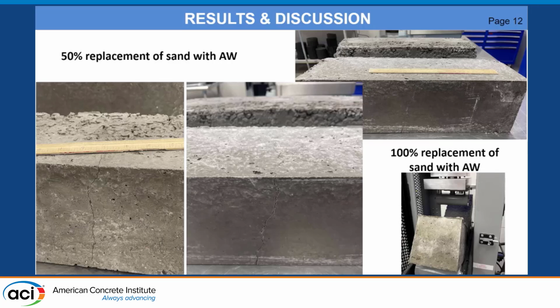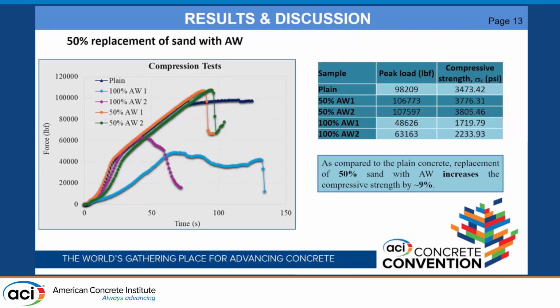So I think that played a lot into it as well. So you can see these are our samples here. They had really good failure, in my opinion. Nice crack right down the middle, and so yeah. And as far as compressive strength goes, again, it was very promising. We saw a couple hundred pounds gained with the 50% replacement as compared to the plain sample. And again, if you compare the 100% to the 50% replacement, it's pretty jarring. But overall, we saw a 9% increase with the 50% replacement this year.